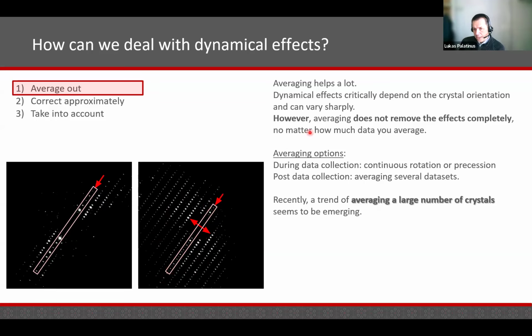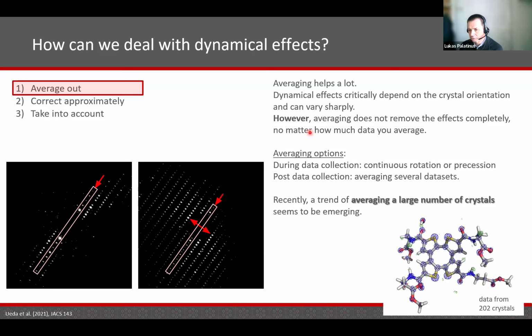There are various ways of averaging the data. Either during the data collection, you can average by applying continuous rotation to the crystal, or you can use so-called precession electron diffraction, which is a special geometry that makes the beam move on a conical path. But also after data collection, you can do the averaging by simply averaging over several data sets. And recently this trend seems to be emerging. For example, this here is an example of a crystal structure determined very nicely. All atoms are there, even hydrogen atoms are visible here in the difference Fourier map. And this structure was obtained by averaging data from over 200 crystals.